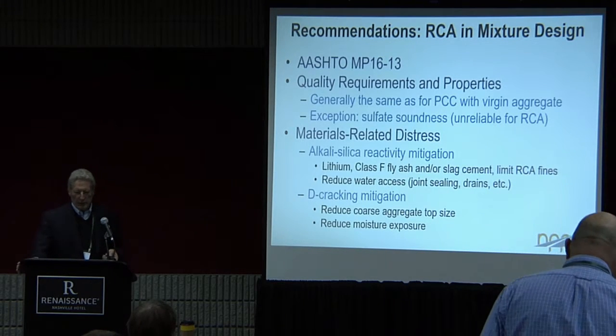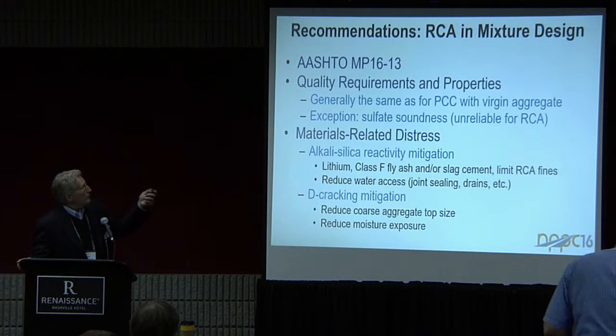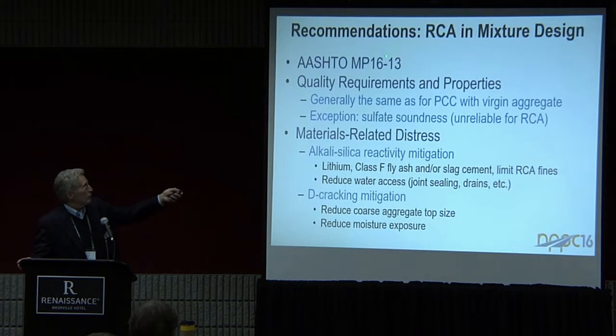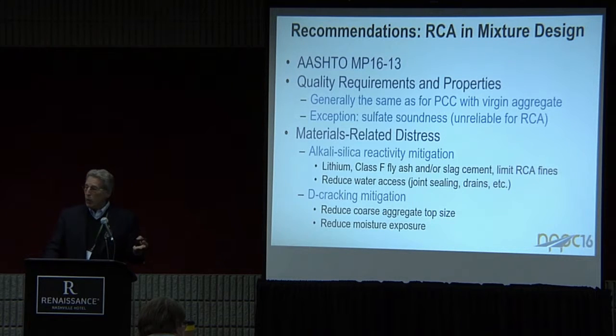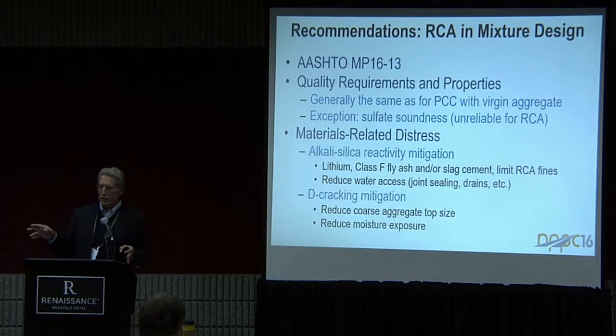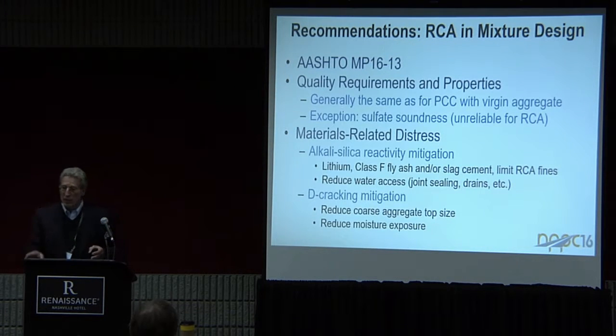There are also recommendations for using crushed concrete in the mix designs. We have a provisional specification, MP 16-13. Basically, quality requirements and properties are pretty much the same as for conventional concrete. The states that have specifications for using crushed concrete in their concrete mixtures basically don't waive any of the quality requirements, and they shouldn't, with the exception of the sulfate soundness test. We've got to find a different way to evaluate freeze-thaw durability because the sulfate soundness test is not reliable for crushed concrete.